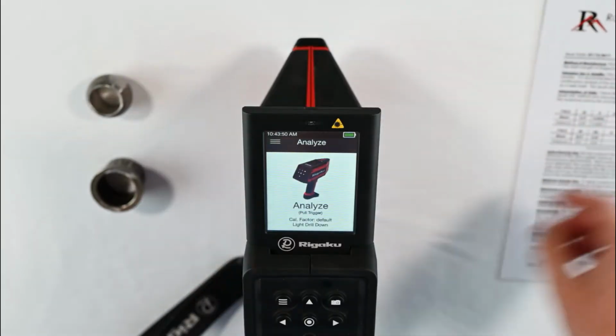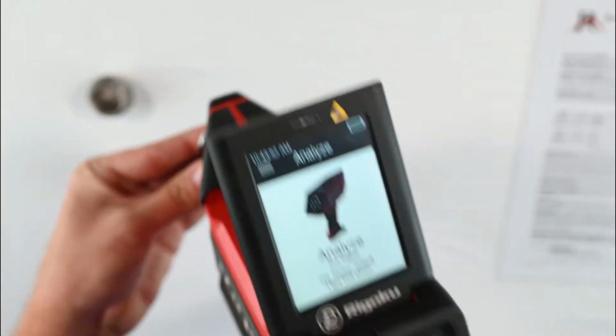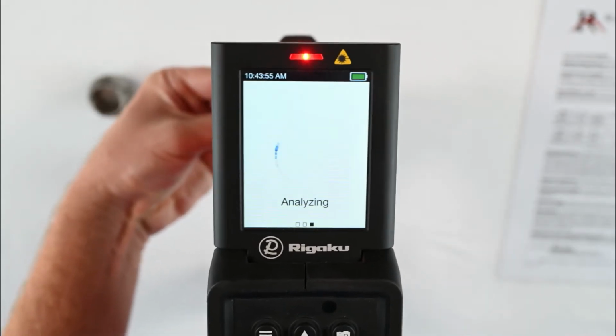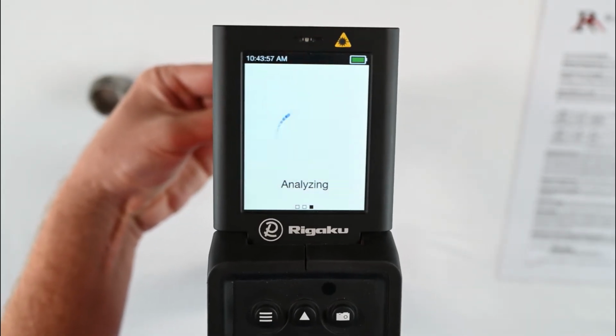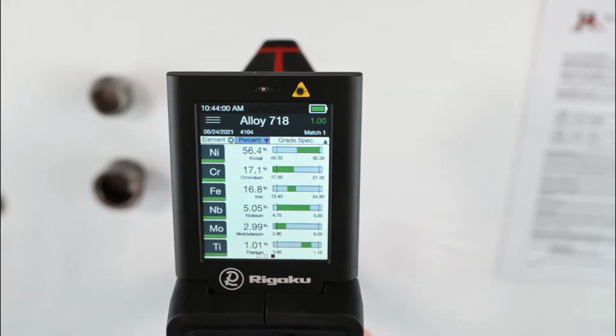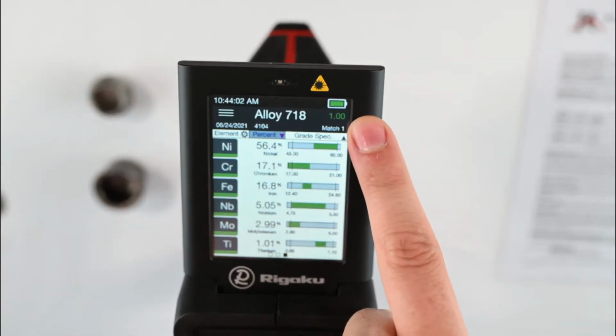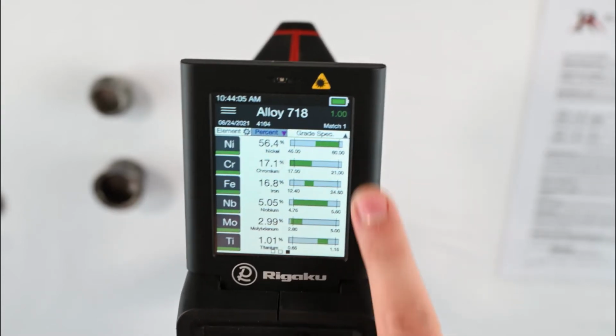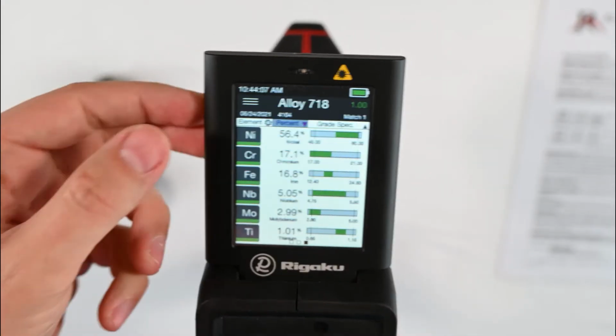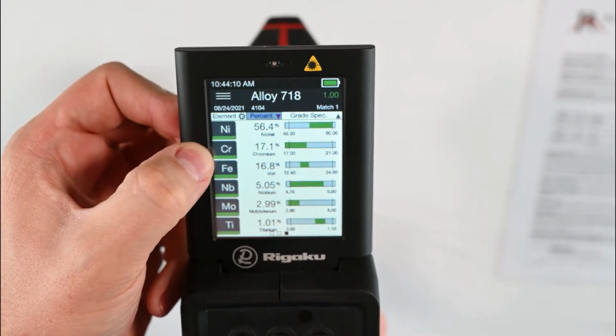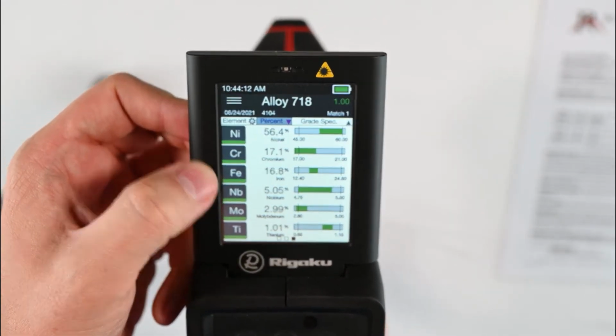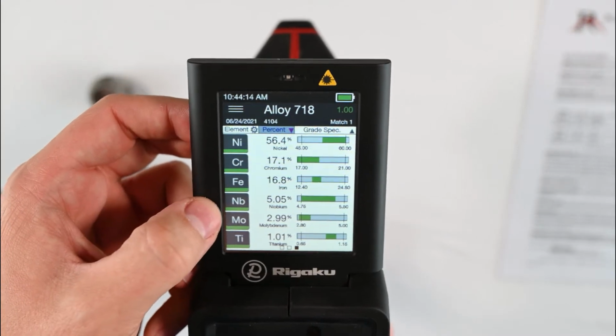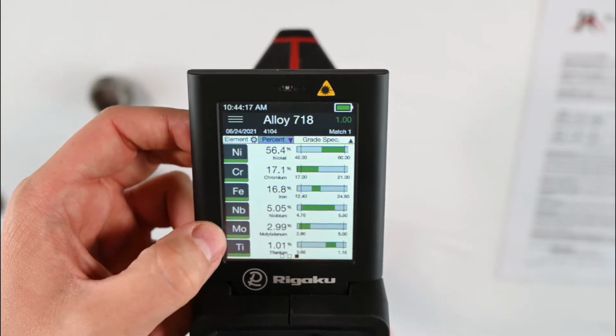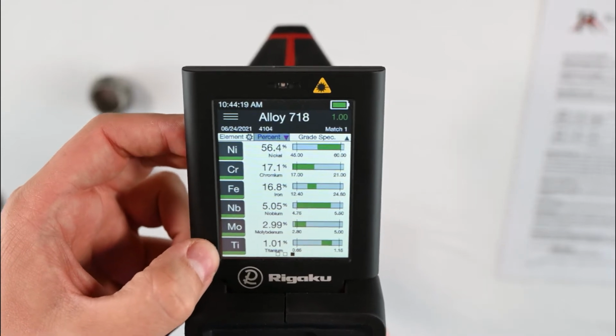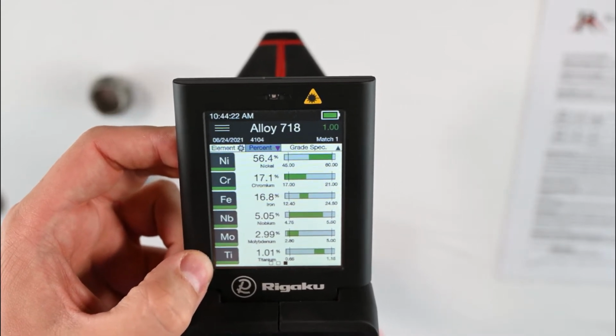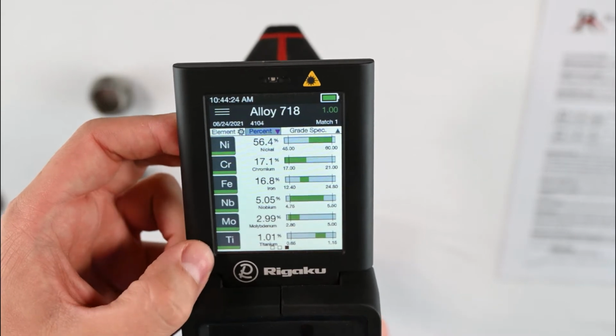So now let's do a live test here and see how that compares to what we get on this 718 sample. So we're doing the test. Okay, so up here in the upper right, I've got a 1.00, 100% match. That just means that this alloy is within the chemical bounds of 718. But as we discussed, chrome is 17.1 is what I read here, about 17% iron, niobium being 5.05%, moly being about 3%, and that little bit of titanium at about 1.01%. I think the published value for titanium is 0.95%, so pretty close.